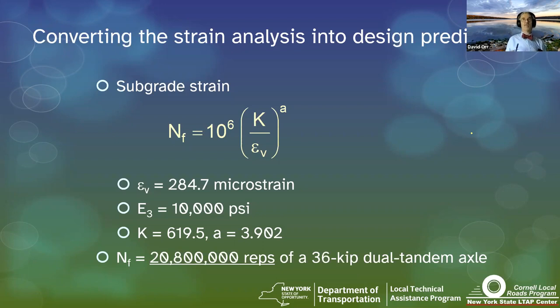And you may have heard a term called perpetual pavement. The idea behind the perpetual pavement is to design it so the surface cracks, and it cracks in such a way that you just do mill and fills literally forever. You keep the strain amounts low enough in the lower layers that you don't have a problem. And it's pretty cool. It actually works.